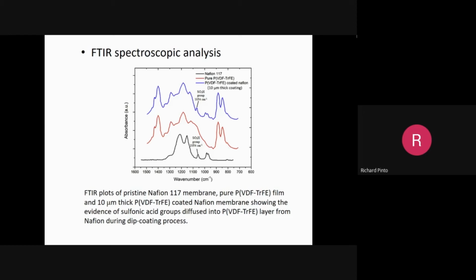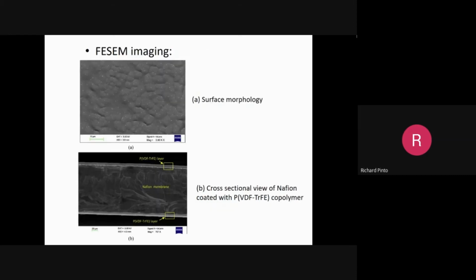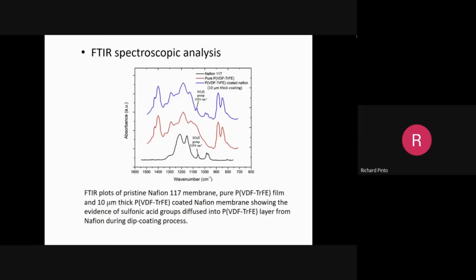See, this is the significance. And there is no sulfonic acid group in the pure PVDF-TrFE. So what is the result? Why is it happening like this? The only way you can explain is the evidence of sulfonic groups diffused into the PVDF layer from Nafion during the coating process. This is not actually spin coating, as I mentioned, that was a mere mistake. It is dip coating. The membrane is dipped into a thin solution of PVDF-TrFE. During the dipping process, sulfonic acid groups diffuse from the membrane into the PVDF-TrFE. That's the only way you can explain this.